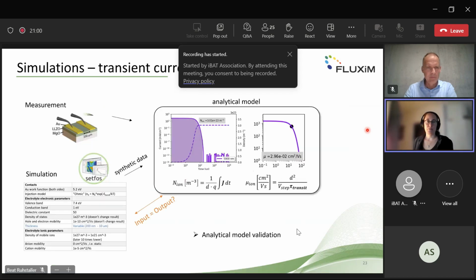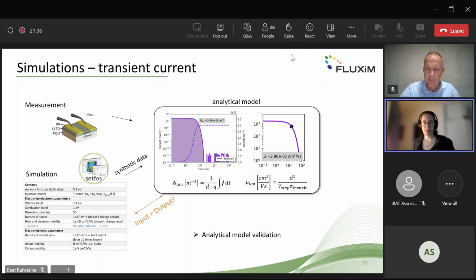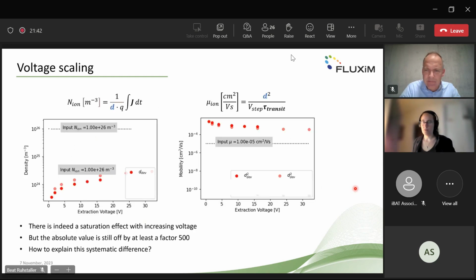Yes, so in our simulation, we basically did the same as in the measurement. We looked at the same curves, but instead of using a measurement technique and using these analytical functions to extract the ion density and the mobility, we used our simulation software that Beat introduced beforehand with certain input parameters to get this synthetic data. And the nice thing about this is that we can compare input and output and thus validate the analytical model. Yes. And then on the next slide, you can see first results.